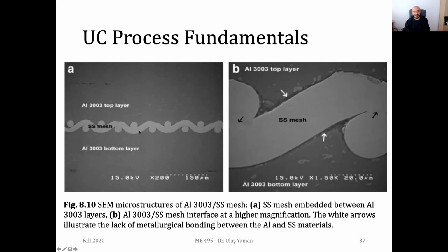It's a very specific case. I think this should be from a study, a research. They are trying to embed such a stainless steel mesh in between. And if you look at the interface here, in some regions we have metallurgical bonds, but in some regions we don't have any. For instance, here at the white arrows, we don't have any metallurgical bonding between aluminum and the stainless steel. So they put this mesh just to increase the quality of bonding between aluminum layers. But it's not a must. It's just for research. They check whether this one is increasing the strength or not.